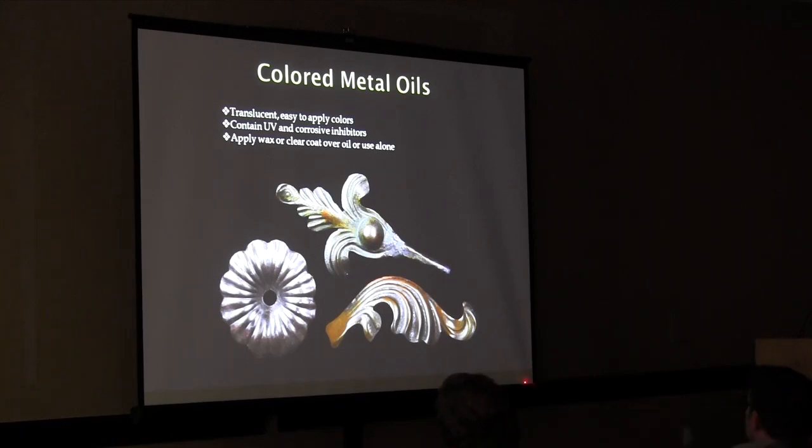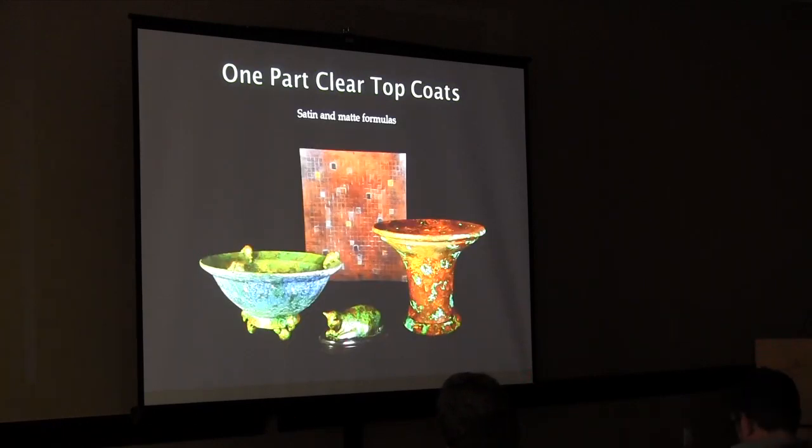Now, oils and waxes, if they're outdoors, don't last a long time. That's the only problem. The best thing I found for outdoors, for iron and steel, is to put the oil on, let it dry for 3 days, and put lacquer over the top of it. That's the best I've ever seen for lasting, outdoors.